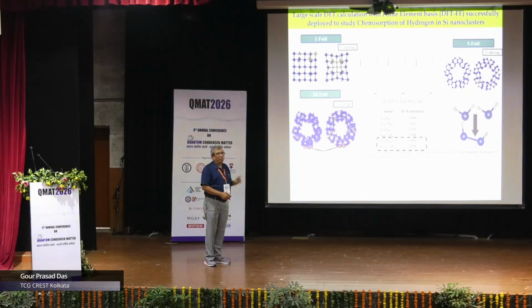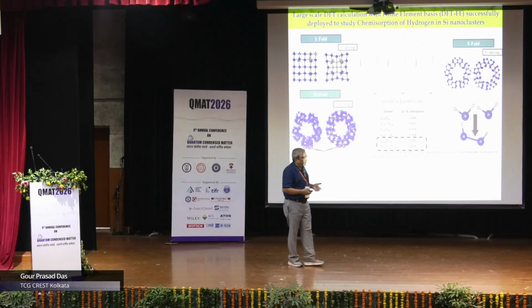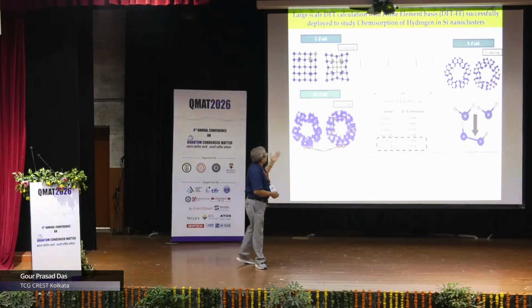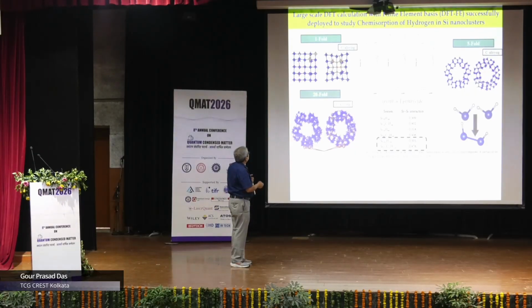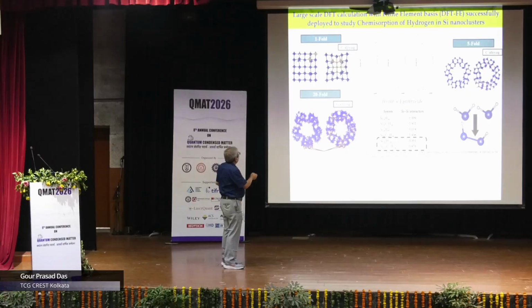One example which we have done recently is an example from material science. The large-scale DFT calculation with finite element basis has been successfully deployed to study chemisorption of hydrogen in silicon nanoclusters. I have been working with my students at IISc a lot on hydrogen storage. If you take a silicon nanocluster and hydrogenate it, the hydrogens will go and sit on the dangling bonds of silicons, okay, fine. Now, you put some carbon, nano alloying the silicon cluster with carbon. As you know, the carbon bond distances being smaller than silicon, the carbon will automatically go to the center. Even if you do molecular dynamics, you will see that it will go to the center.